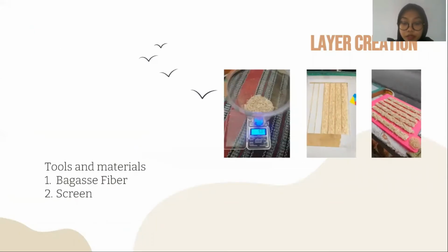In this process, bagasse fiber that has undergone a delignification process and has been cut according to the variant in fiber length is weighed according to the composition calculation as much as 35%. Then, the bagasse fiber is placed in a mold on a screen. Next is mixing water and glue into a basin or container, then pour it over the fiber. And then, pressure is applied to the screen and then dried until the water content is at the minimum level. The dry layer is pressurized using a roll machine until the layer thickness is less than 1 mm.